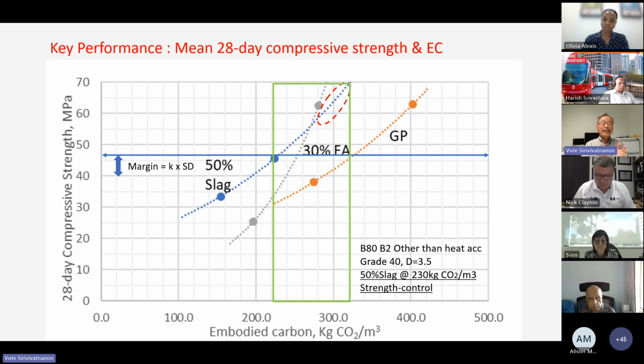In this case, if you look at the 28-day strength, for instance, you can clearly see the influence of concrete with either just GP cement, 30% fly ash, or the 50% slag on the embodied carbon, respectively, of the concrete that will meet a particular strength grade requirement. In this case, it happened that the slag came up, I guess, best with the embodied carbon just around the 220 to 230 kilogram carbon dioxide per cubic meter of concrete.